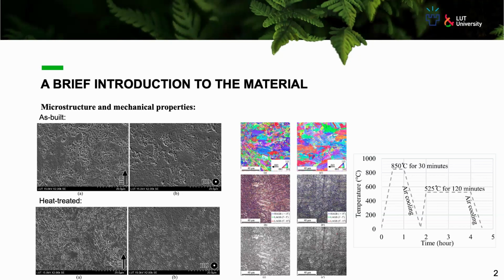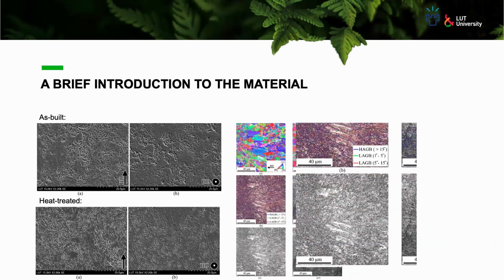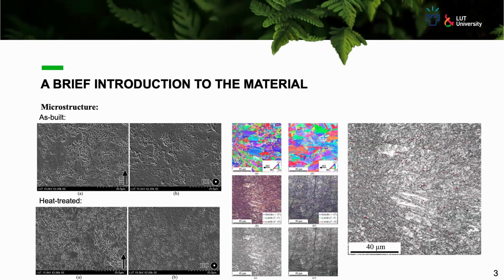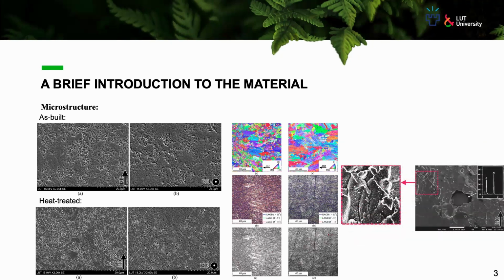And heat treatment caused a difference in the balance of the high angle grain boundaries and low angle grain boundaries. In addition to the martensite in the background phase, we also detected some minor amounts of retained austenite as red dots in this image, and the amount was below 1%. However, this below 1% retained austenite can have an important role in the mechanical performance of this material, as I will explain later. And of course, after heat treatment, we can observe these nanometric beta particles that have a huge contribution to the strength of the material.